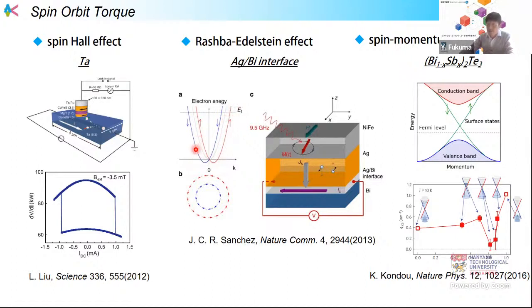In the case of the momentum with direction, we can get that downspin. Then we can see this kind of spin to charge conversion behavior at the interface. Also, in the narrow gap semiconductor, in the case of the bulk, the gap is open, but at the surface state with the spin orbit interaction, we can get this kind of spin polarized surface only for the surfaces.